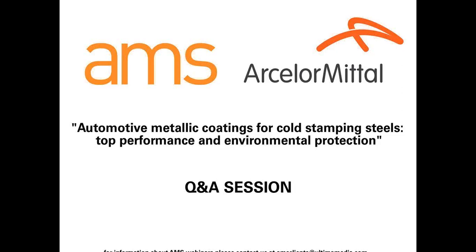So for unprotected stamped edges, there is, in fact, an optimum ratio to have between the coating thickness and the substrate thickness. The higher the thickness of the edge to reprotect, the higher zinc magnesium coating thickness you will have to get. But especially with Magnelis Protect, we have an effect of reprotection of the uncoated edges, thanks to the thickness of the coating, which will form protecting compounds on the edges of the steel.